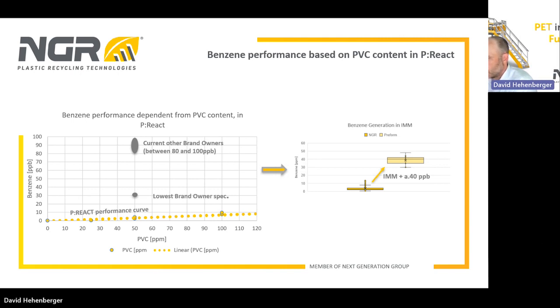And there's an additional risk when you produce preforms from the pellets, because we have to consider an additional increase of benzene in the preform production. So if the benzene is very low in the pellets, the chance to have a low benzene increase in the injection molding process is very good. If the benzene value in the pellets is already very high, in the range of 40 or 50, then you can have a couple of hundreds in the preform, sorry.